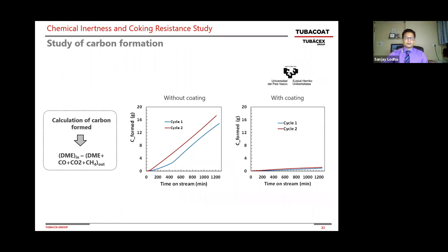So this slide shows the carbon forming reaction. Basically we just do the equation through which we know how much carbon is formed. And again, what you see here is without coating and with coating, there's a huge difference in the amount of carbon that you make, a factor of 10 times lower carbon formation. Next slide, please.